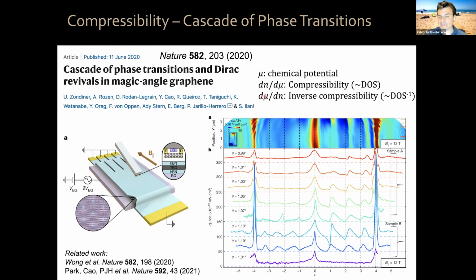In particular, they can measure the derivative of the chemical potential with respect to density, which is called the inverse compressibility. The compressibility is the derivative of the charge density with respect to chemical potential, and in single particle physics it is proportional to the density of states. The inverse, d mu dn, inverse compressibility, you can think of as the inverse of the density of states, okay? So gaps, Dirac points, they appear as peaks, okay? So what Shahal and his collaborators saw is that if you scan on a magic angle twisted bilayer graphene device, where they can go locally to regions with different twist angles, as a function of filling factor, they observe a sequence of sawtooth type of behavior, which we call a cascade of phase transitions, okay?